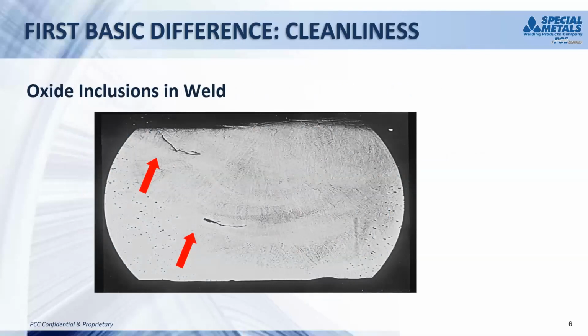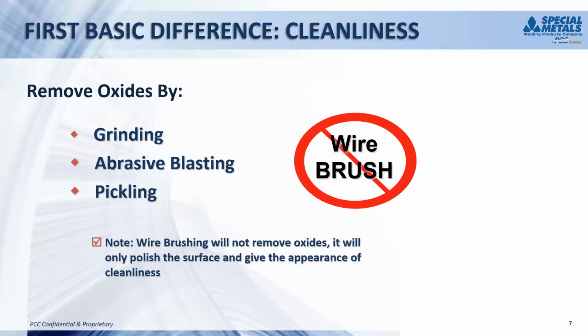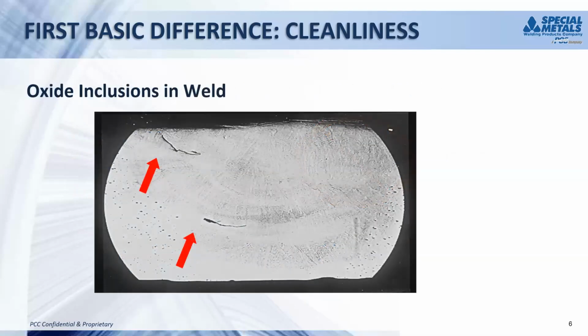And if you try to weld through the oxides in nickel alloys, typically you can get inclusions like you see on the screen here. And you can imagine what that would look like if you tried to cut a transverse side bend through that and bend it. It'd pop open. And if you didn't find those in your quality assessment of the plate, it might cause a problem in service. So we got to get rid of the oxide inclusions. Next slide, John.